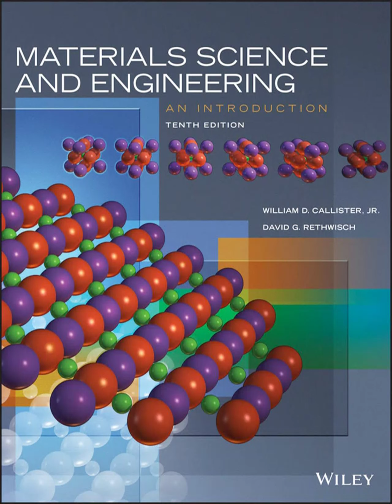Exactly. And this knowledge is what allows engineers to precisely design heat treatments. Going back to that steel gear one last time, if you need a specific carbon concentration at a certain depth for proper hardening, you can use these equations and constants to figure out the required time at different temperatures. Maybe it's 29.6 hours at 900 degrees C. Or maybe just 5.3 hours if you crank the heat up to 1050 degrees C. Right. You can trade off time and temperature to get the result you need, all based on controlling diffusion.